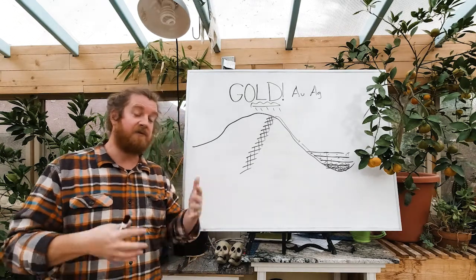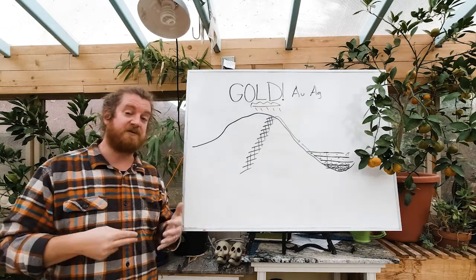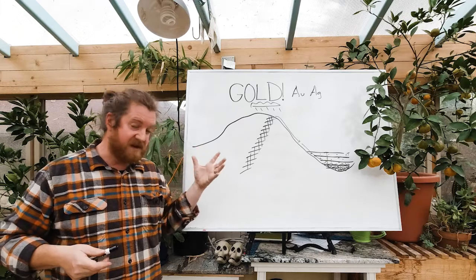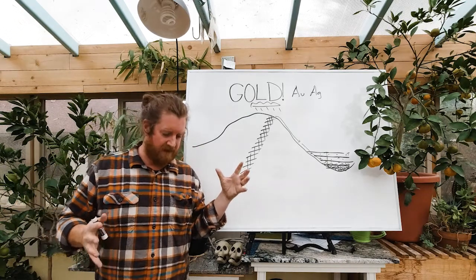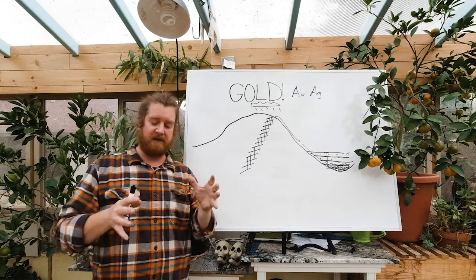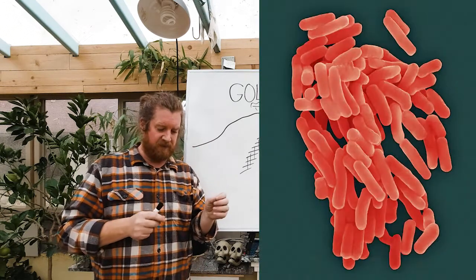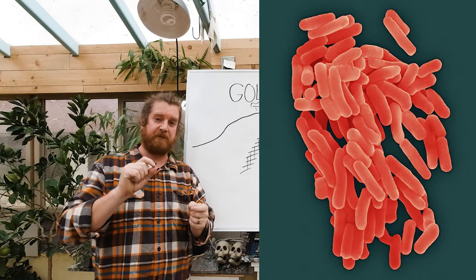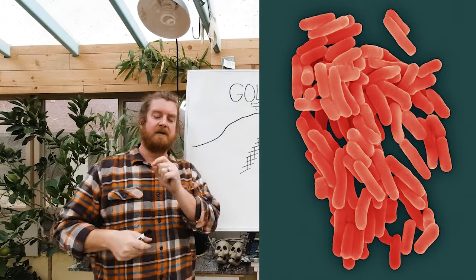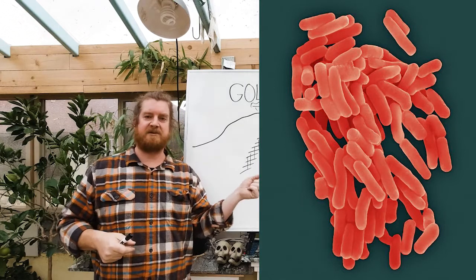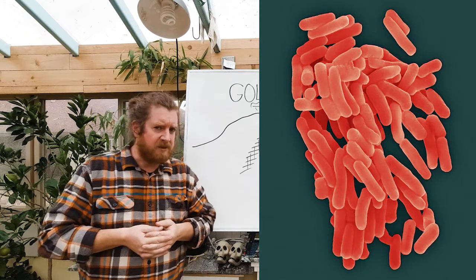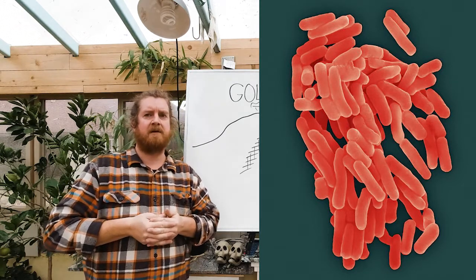Things that live on the hydrothermal vents in the seafloor use chemosynthesis. And so we can get some chemosynthetic archaea or bacteria and inoculate this ore, just like we were talking about, and it will go into minerals that are bonded with sulfur in particular, and it will strip the sulfur off and consume it, leaving us with the concentrated metal behind. So that's called biomining, biological mining, or bioleaching.